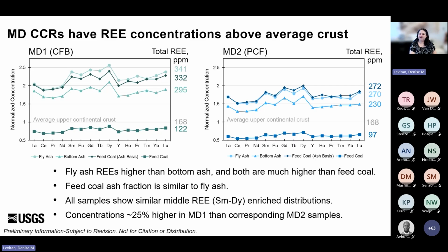Another thing to note here is that the most enriched relative to upper continental crust rare earth element here is dysprosium, Dy, terbium, just to the left of it, Tb, also relatively enriched. And then cerium, the second one in, is fairly low. And in terms of processing and economics, that's a good sign because having more of those generally more favored rare earth elements relative to cerium, which is often considered excess, that's a good sign in processing, more favorable economically. So those are the rare earth element concentrations.